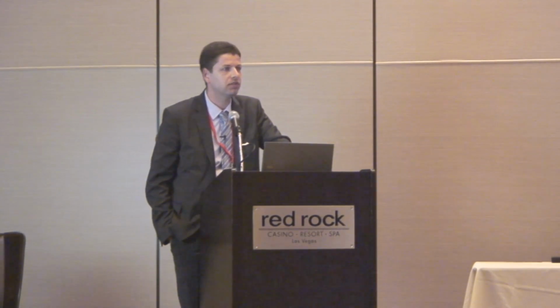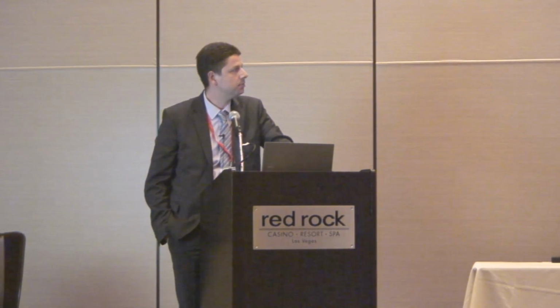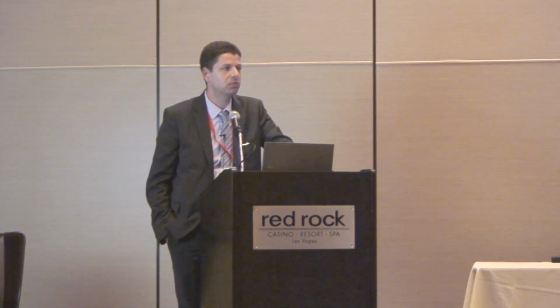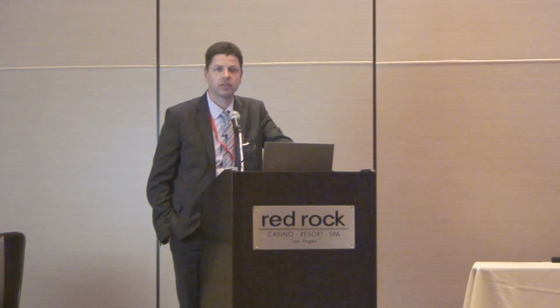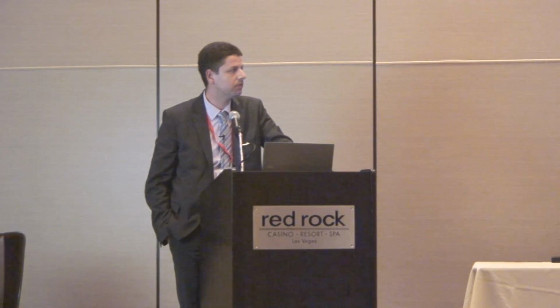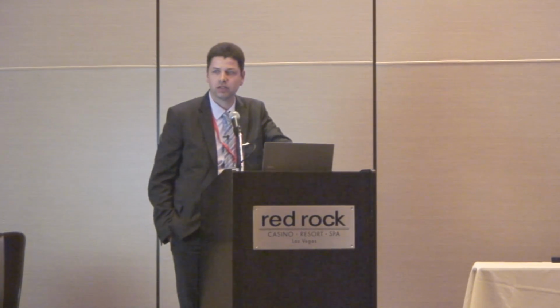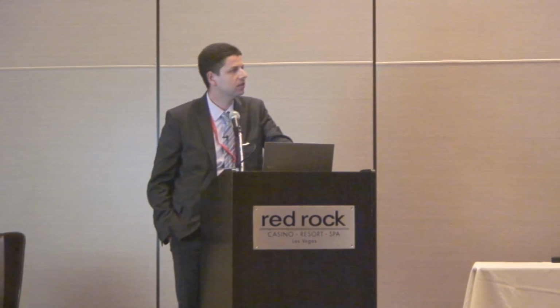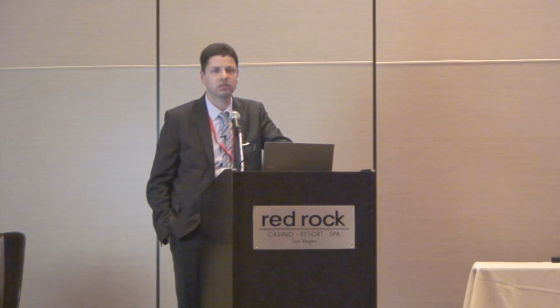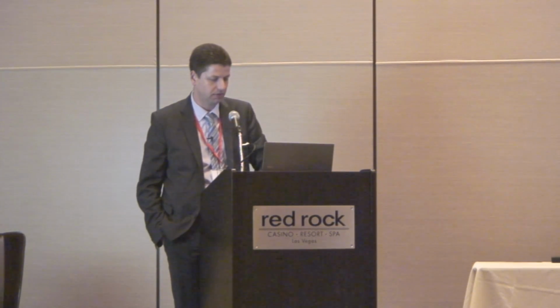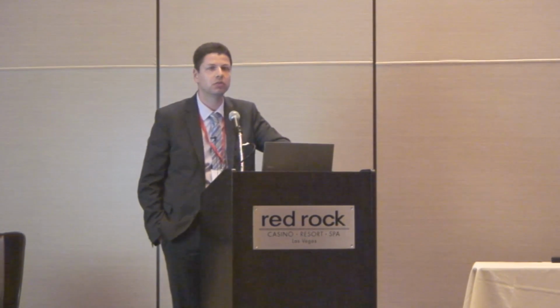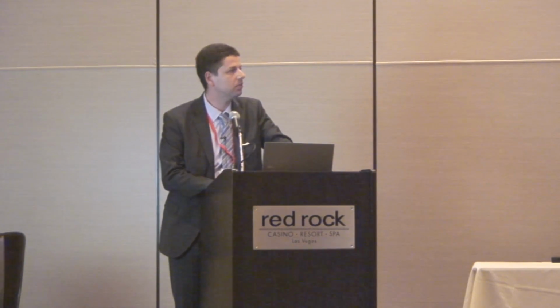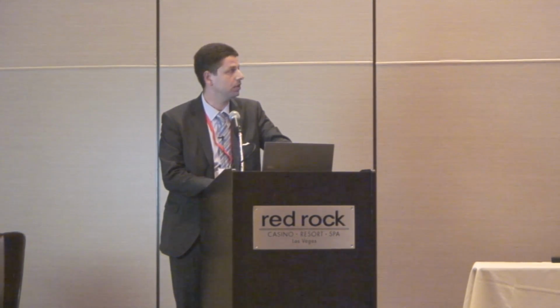After that presentation, we did ongoing work. We presented the influence, or what is the optimum foil width a customer should use to get the best results after brazing to protect his cemented carbide tips, and that was a result we found during that time. But there's still an ongoing question from our customers: what is the optimum brazing gap width when we braze cemented carbide, when we braze the saw blades? And this is what we tried to do during this investigation, and we did practical things and finite element calculations.